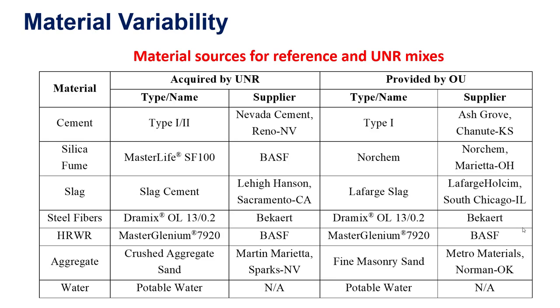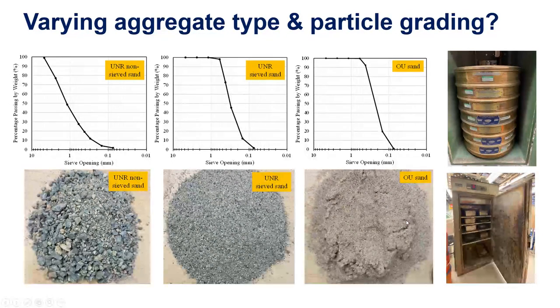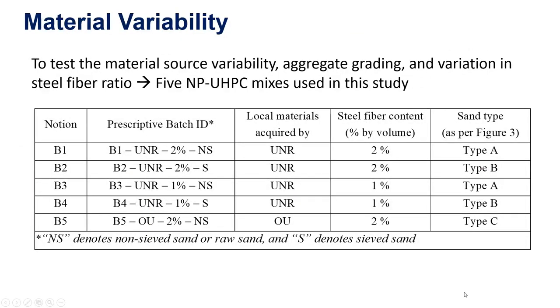For the material variability portion, we sourced ordinary cement, silica fume, and slag — most materials from the western side of the country from different suppliers than those used by the University of Oklahoma — and did an apple-to-apple comparison. We also varied the aggregate type and particle grading, comparing non-sieved coarse sand and sieved uniform-graded sand with the fine sand originally used at OU. We ran five batches and varied the steel fiber ratio to see if one percent would yield acceptable mechanical properties for bridge decks.